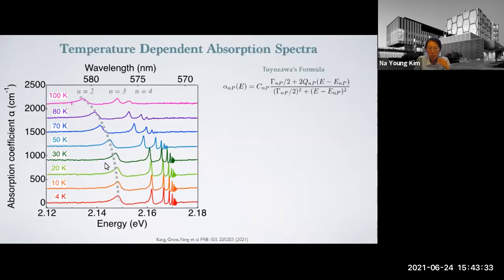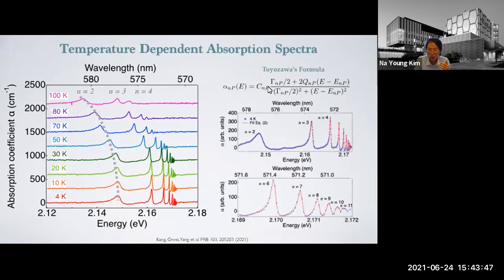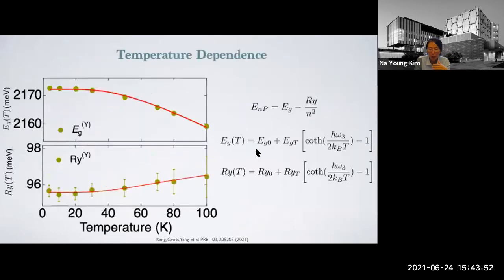Notice also that the shape of the peak follows the Toyozawa asymmetric Lorentzian formula, so we can fit that to extract parameters to quantify it. This is one of the fitting attempts. Once we have that, we see the temperature dependence of the redshift for the band gap, which is related to the lattice constant, and also the Rydberg constant, as a function of the cotangent hyperbolic in temperature.